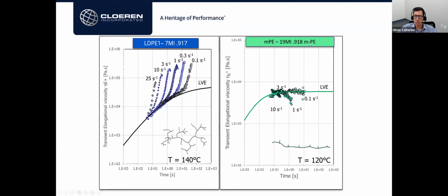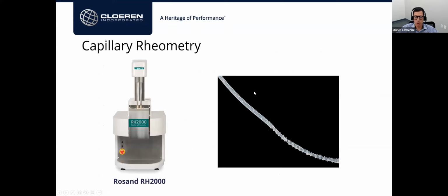As you can see here, the metallocene grade, with a very linear molecular structure, did well. The measurements were actually quite difficult, but you can see that there's no strain hardening at all at any strain rate. So these tools are really great to compare viscoelastic behaviors, investigate the molecular structures, and relate that to processing.